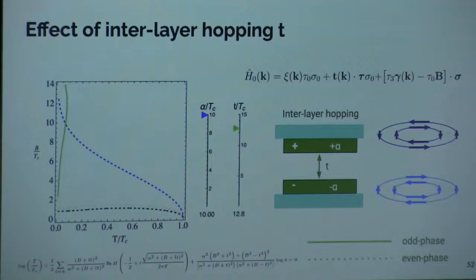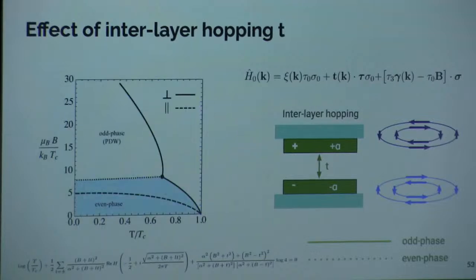However, whereas the even phase suffers due to the magnetic field, the odd phase is robust against the magnetic field. So now to obtain the true critical field, you should look at the combined dashed green and solid lines. And this typically gives us something like this, where you should look at the solid black line, where at high magnetic fields there is an odd phase, and at low magnetic fields there is an even phase. And since you cannot continuously deform one order parameter into the other, the transition necessarily needs to be of the discontinuous first order type.